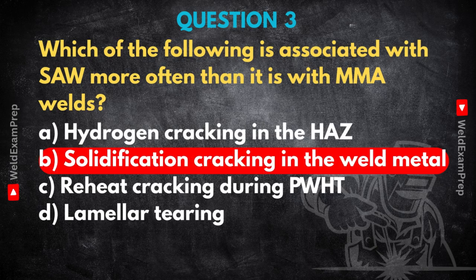Solidification cracking. Okay, yeah, sometimes called hot cracking. It happens right as the weld metal is freezing, solidifying. It's mainly a concern in processes that create a large, deep weld pool, and SAW definitely fits that bill. The larger weld pool in SAW, plus its typically slower cooling rate compared to MMA, means the metal stays molten for longer. Right. And that gives more time for impurities, things like sulfur and phosphorus, to segregate, to gather in the last bits of liquid metal to freeze. These impurities can form weak films at the grain boundaries, which then crack open under the shrinkage stresses as the weld cools down. Makes sense.